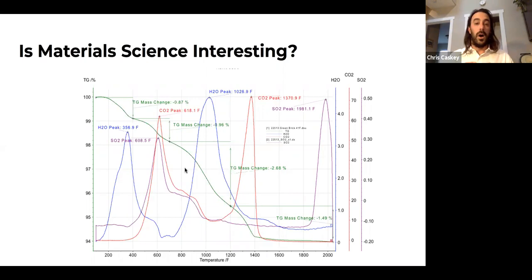To get this CO2 out, we have to get oxygen into the clay body, react it with the carbon, and CO2 back out. So we need some level of porosity for that gas exchange, but we want a minimum porosity because we need those nearest neighbor agreements so that they can fuse together and be extra strong. And of course, in the final product, porosity is going to soak up water and cause freeze-thaw if the application is outdoors. So we have this balance between we want porosity originally, and then we want that all to seal up at the end.